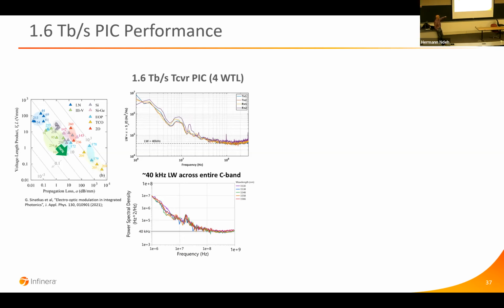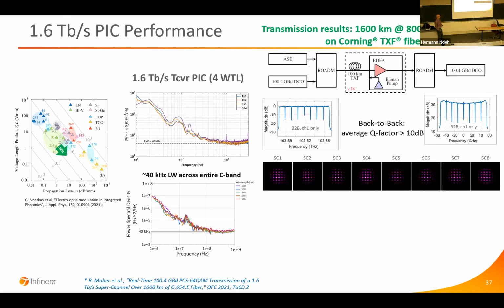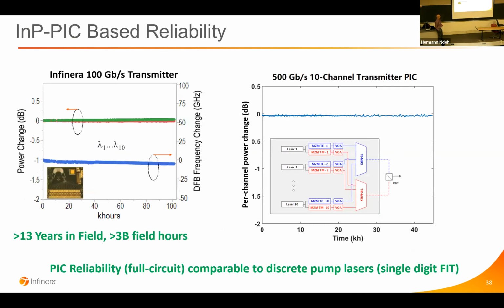In addition, the lasers on these devices were 40 kilohertz in line width. So at the time, these were the narrowest line width lasers that were reported. And the devices were highly reliable. So this is 40,000 hours for a chip that's got over 50 functions, has the same reliability as a single submarine pump laser.